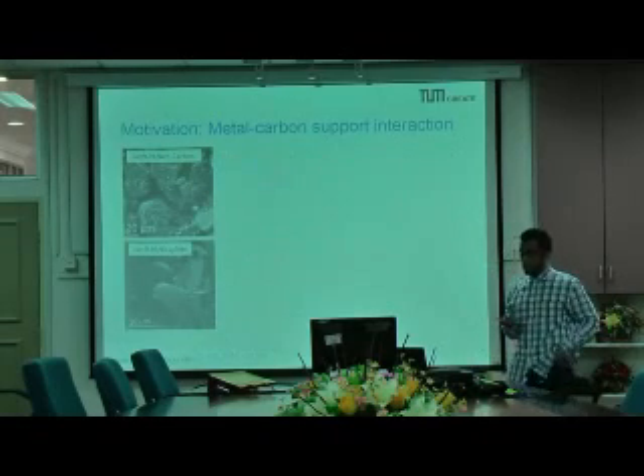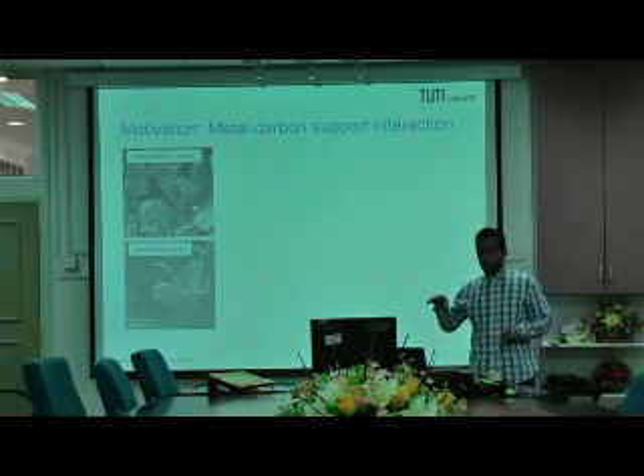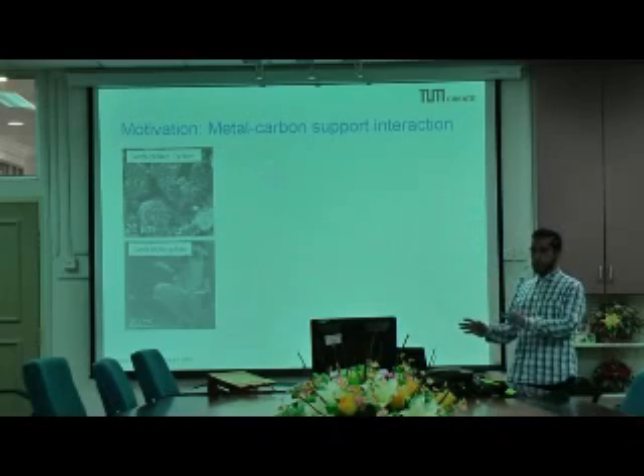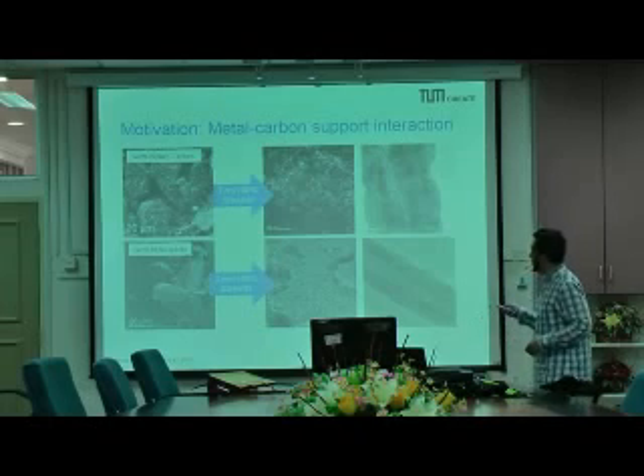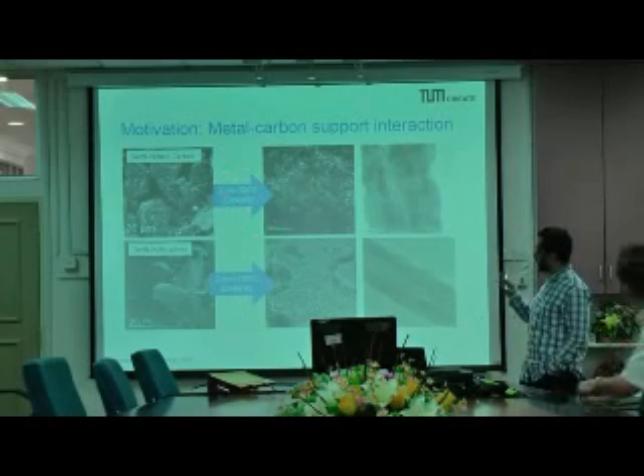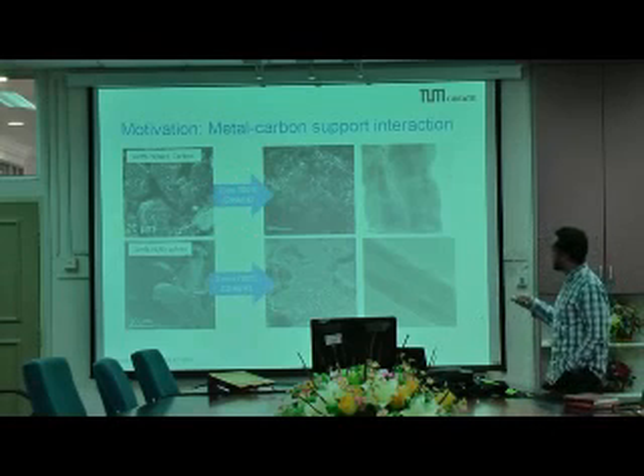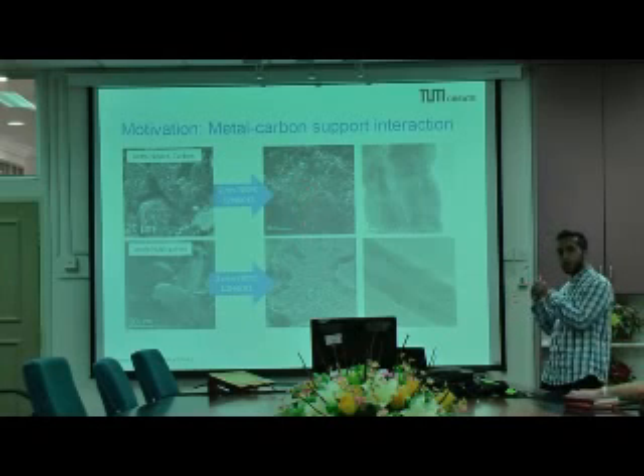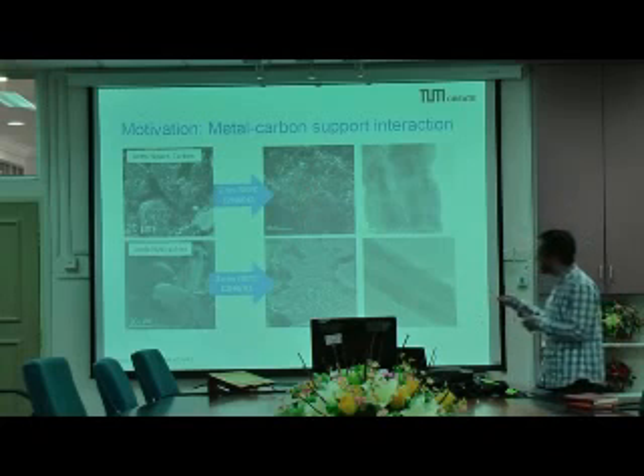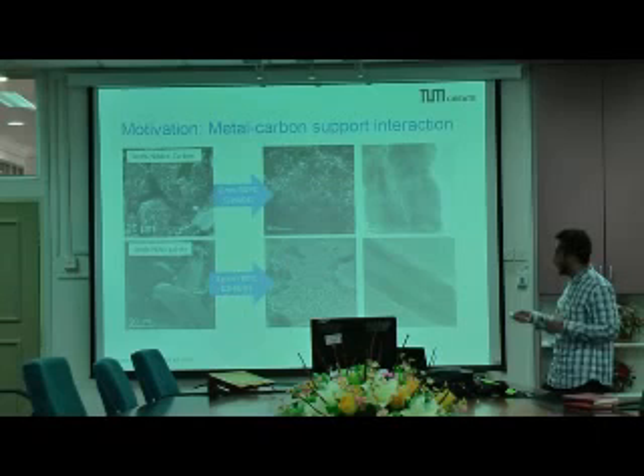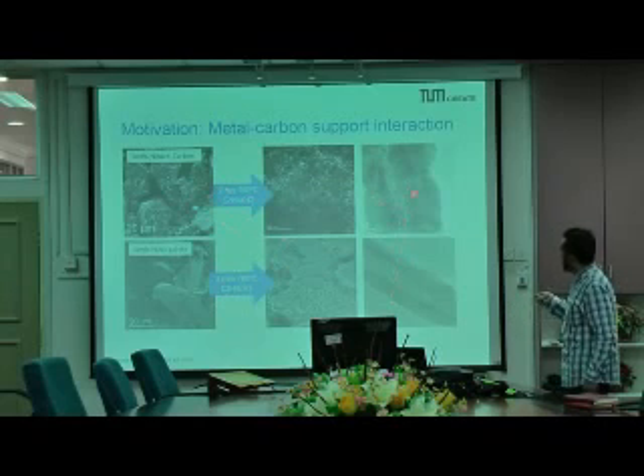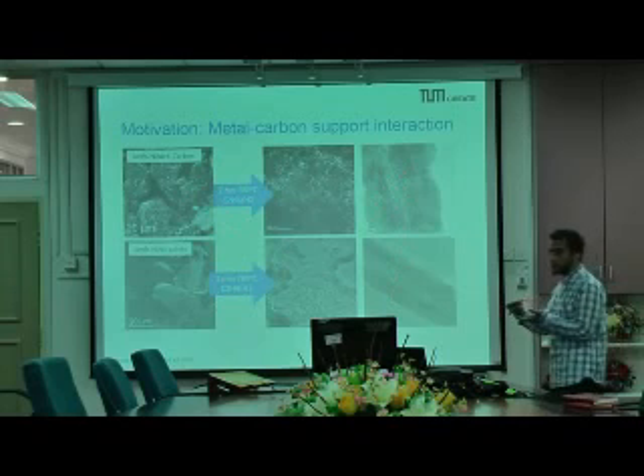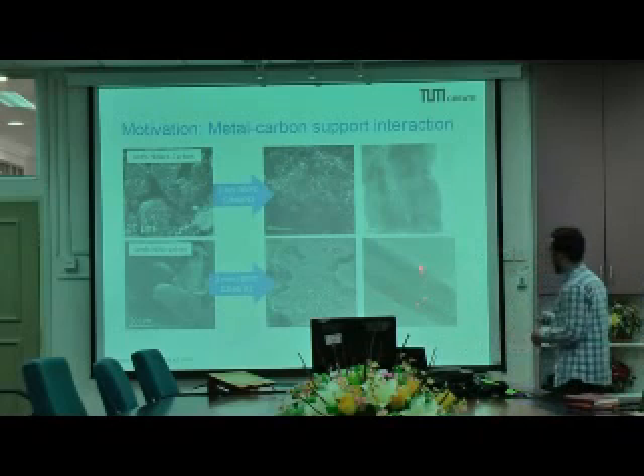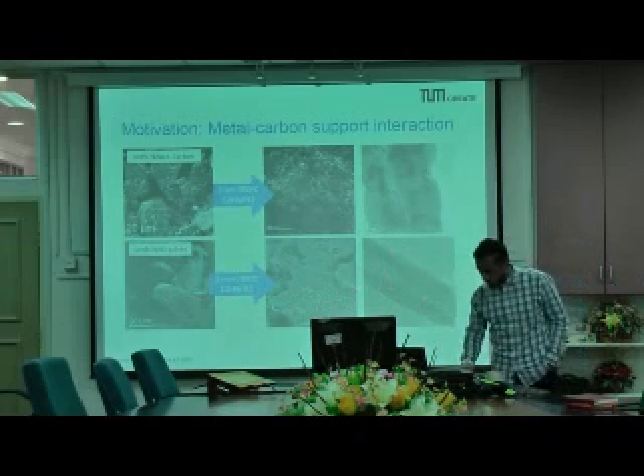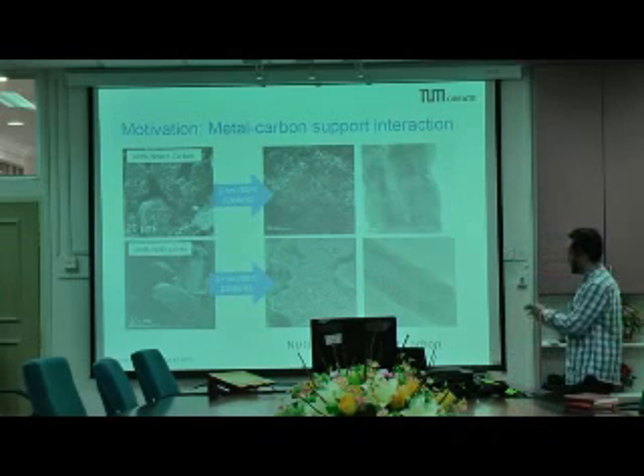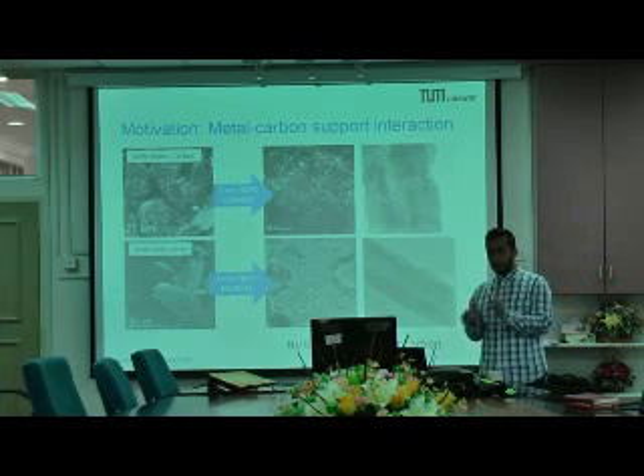Another motivation is that in our preliminary experiments, if we try to grow carbon out of two different structures, activated carbon, which is quite an amorphous structure, and graphite, you get very different results. Here you see at 700 degrees, where the precursor is decomposed, forming pyrolytic carbon and hydrogen, you have a different density of material, indicating that the growth rate is quite different. Do notice that these were taken after 2 days for graphite and 2 hours for carbon. And the structure is quite different. There's a slight irregularity in the graphitic arrangement if you grow them on active carbon, whereas it's quite well oriented if you grow them on graphite. So overall, in short, graphite is a way better carbon support for these reactions.